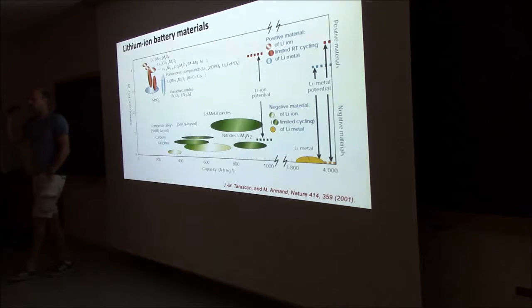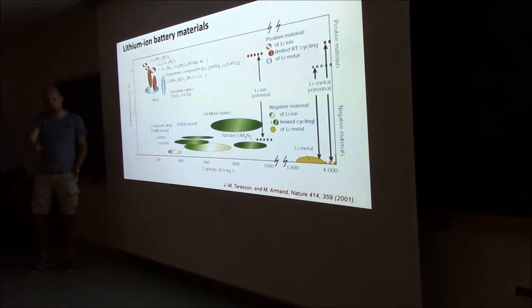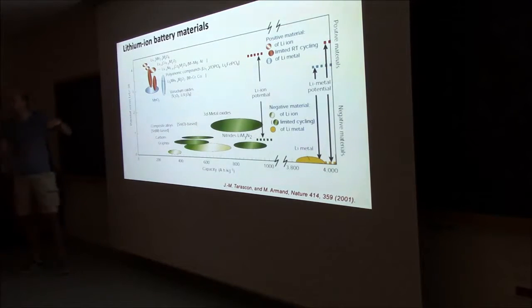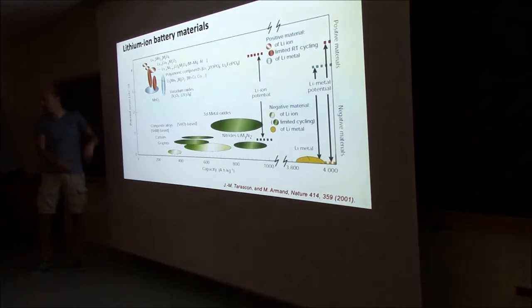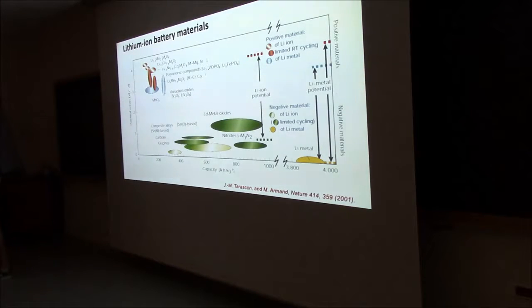You want as high as possible a potential against lithium. Here you see the cathodes. You want as low as possible, so that when you combine them, you have the maximum voltage between them. So what do we use? We use, for instance, graphite. It's cheap, and you can see it's pretty low, so you have a big voltage. If you look at the capacity that you can get per kilogram, you can see the anode is better per kilogram than the cathode materials. So most research in batteries is done on the cathodes to improve this.